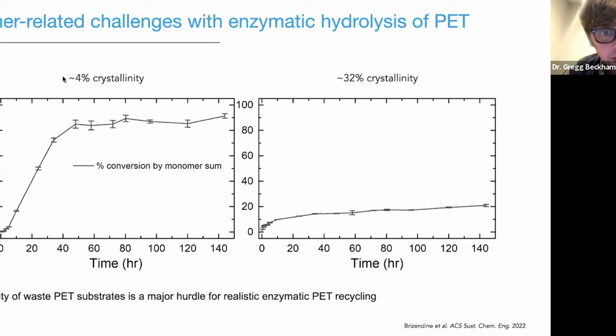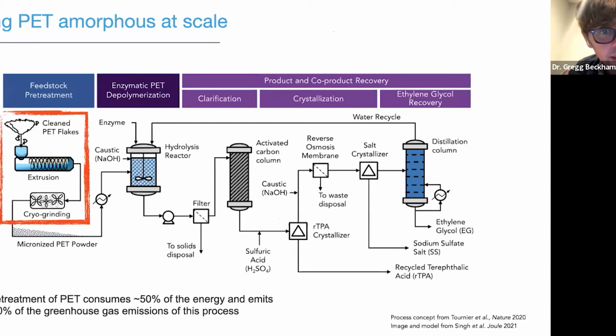And what you can see is if you look at the low crystallinity PET, you're able to essentially get nearly quantitative conversion. It's about 95% plus conversion. But when you use essentially bottle grade PET or highly crystalline PET, around 32% in this case, you can see that the enzymatic hydrolysis tops out at about 20% conversion. The crystallinity of PET substrates is a major hurdle for realistic enzymatic PET recycling, because the energy intensity needed to take this kind of polymer over to this type of polymer is quite substantial. And I'll show you why on this slide.